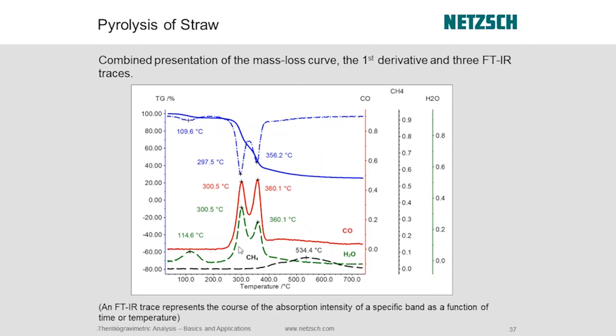So here's evolution of CO, for example. In this big step here, we see how that correlates to the evolution of CO. It also has correlation to evolution of water. But we also see in that first mass loss step, hey, there's some water, and there's no CO coming off. So we can take a good guess that that's the moisture, the water that's trapped or bound inside the straw. And then we see methane. So as we take this further into the decomposition, we see production of methane here at around 500 or so degrees, and at the final step that's going on. So if you haven't thought about evolved gas analysis, you can really see some of the horsepower that comes into play.